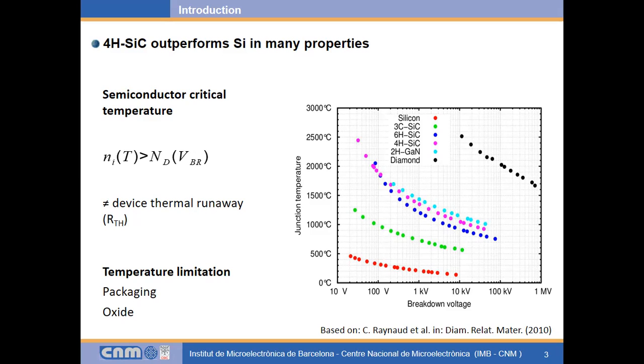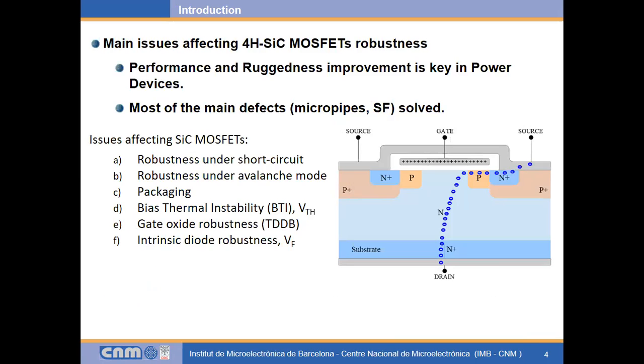Then why are we not working at higher temperatures? Well, there are other limiting factors, such as packaging, and besides, the oxide is another limiting factor in silicon carbide MOSFETs. Performance and ruggedness improvement is key in power semiconductor devices. In silicon carbide MOSFETs, most of the main defects which have impeded their commercialization until now are now solved, such as micropipes or stacking faults, but there remain other issues compromising their reliability, such as robustness under short circuit, robustness under avalanche mode, packaging, bias thermal instability, gate oxide robustness, and the intrinsic diode robustness.